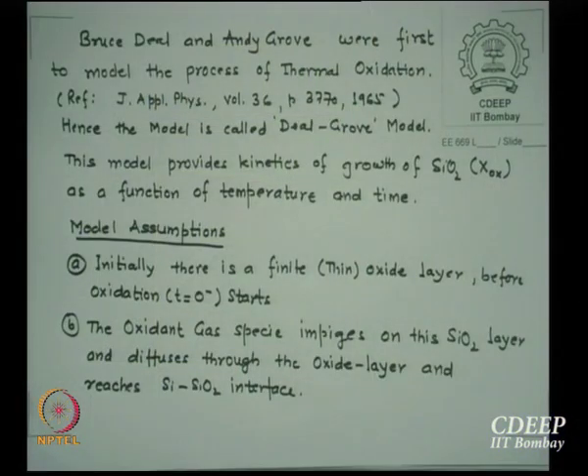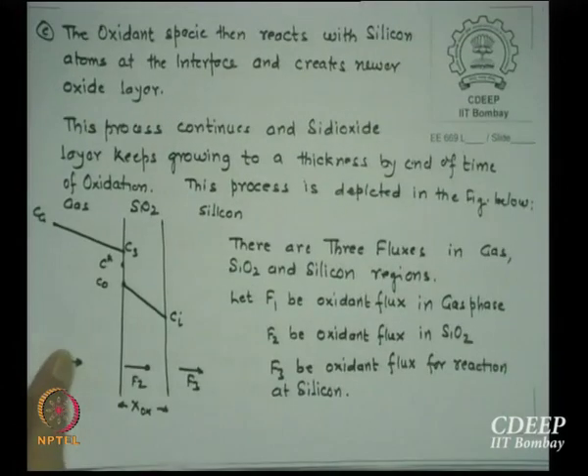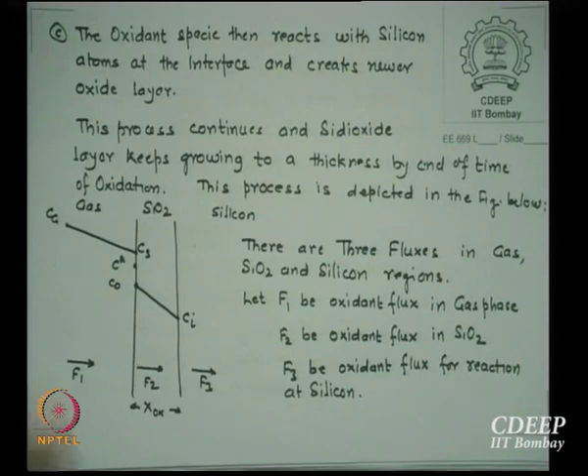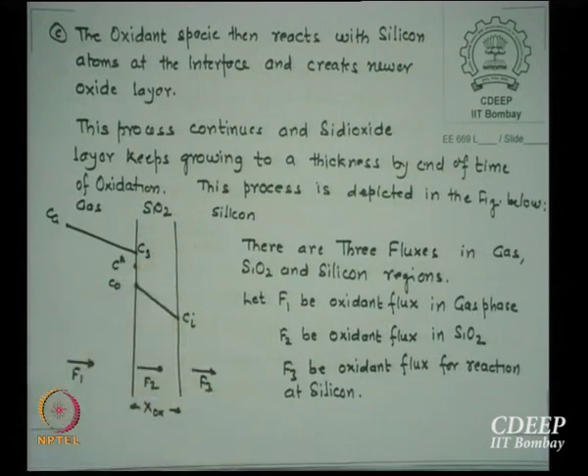Okay, so the assumption he made was that initially there is a finite thin oxide, and at t equal to 0 minus this oxide is available, and at t equal to 0 plus the oxidant attacks this silicon dioxide layer and starts the oxidation. We did this last time, I'm just trying to recapitulate. The oxidant species diffuses through the thin oxide, reaches the silicon-silicon dioxide interface, and reacts with silicon to form SiO2. We have already said there are three fluxes: F1 in the gas phase, F2 in the oxide, and F3 near the silicon-silicon dioxide interface.